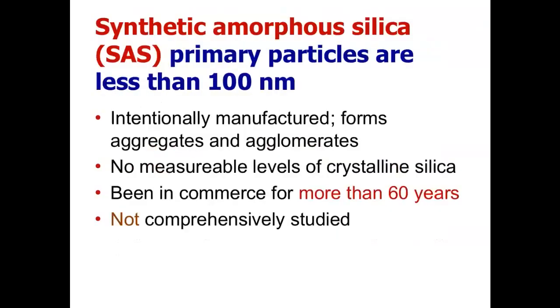Another material that's been manufactured in large quantities is synthetic amorphous silica. Primary particles are mostly in the nanomaterial range, less than 100 nanometers. This material is intentionally manufactured. It forms aggregates and agglomerates. There really isn't an issue with measurable levels of crystalline silica. And again, this is a material that's been manufactured more than 60 years, but not comprehensively studied.